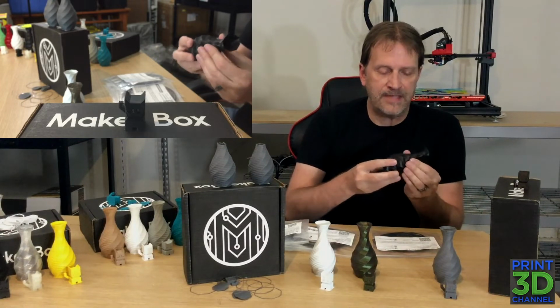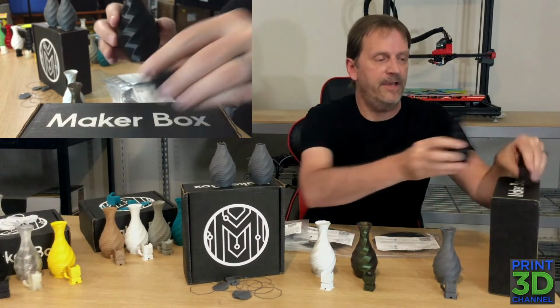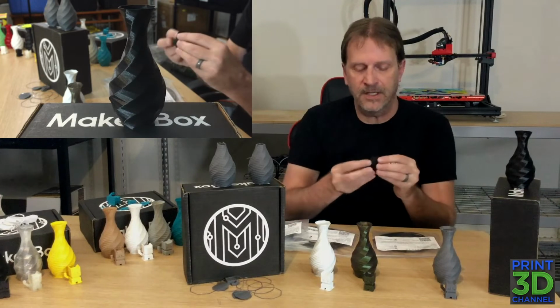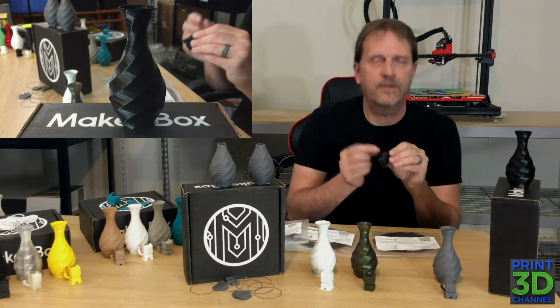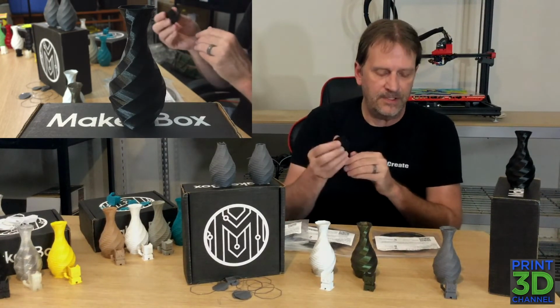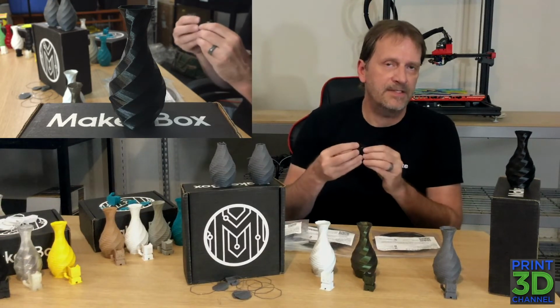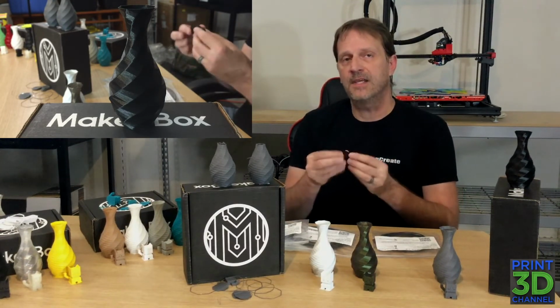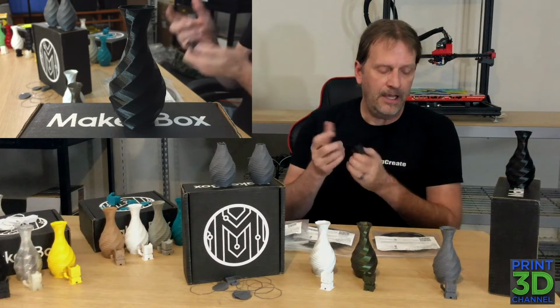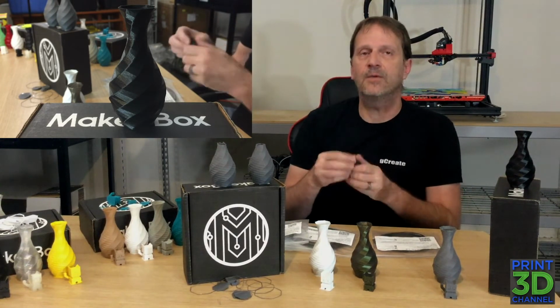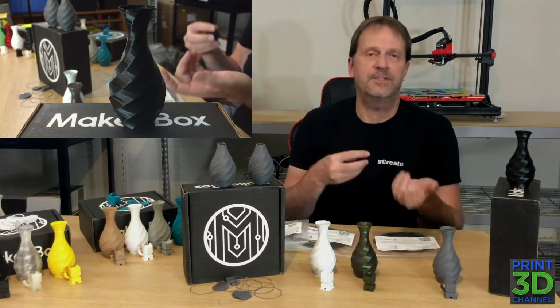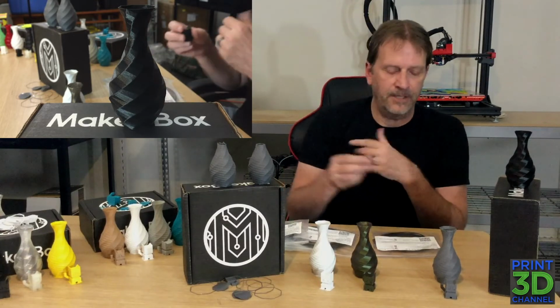So it really brings out all the polygons on the rose twist vase. And on the Cali Cat, I did have a little bit of melty issues in these front corners where the extruder stops, because we did start this at 215C and I dropped it down to 210C when I saw that that was happening. Our bed temperature was set to 50C, which is our normal print temperature for PETGs and PLAs. I didn't bring it up to 60C.